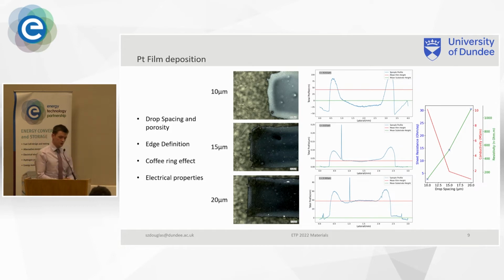So they're surface profile measurements measured with a DekTak. That's after annealing, so that's the platinum film. That spike will be dust. Oh, no, so you know it's kind of got two shoulders on them. Yes. So what we're observing there is the coffee ring effect. When you deposit the solution, like a coffee cup, you find a ring on the outside. This is usually a sign that your solution is particulate, as the particles, with the capillary motion, move to the outside. Our ink is supposed to be non-particulate, but we still observe this.